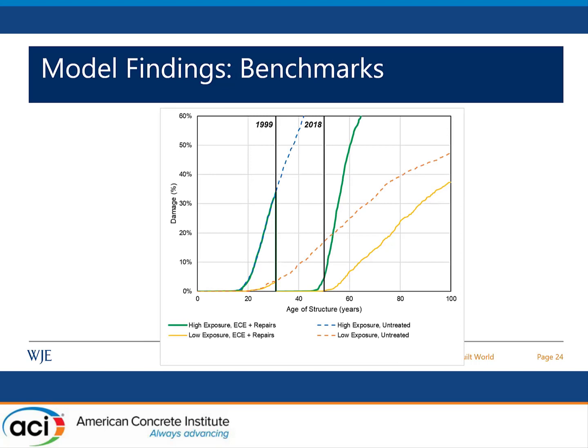Additionally, when we looked at the amount of damage that was predicted in both the cases of high and low exposure, in cases with ECE and repairs, and in cases where there were untreated piers, we compared that to the observed damage that was documented in the 1999 inspection and also in our 2018 inspection, and again found very good correlation between the observations of both studies and what our model was predicting.